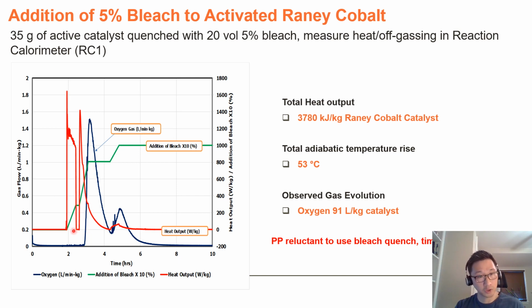The green trace represents the addition of the bleach. The red trace represents the heat output. The blue trace represents the off-gassing. And what you notice is that once we start adding the bleach, there's an immediate exotherm. In fact, there's so much heat we actually have to wait for the reaction to cool down before we add the rest. Now, once we resume the bleach addition, we notice another exotherm and very significant off-gassing here, and the gas we later identified as oxygen.